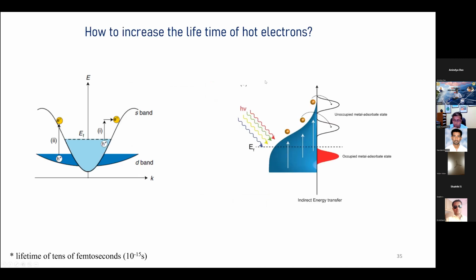So then the question we ask is, why? If the material is so black and absorbs a large number of photons, then ideally it should show good catalytic activity, better than normal gold particles, but not really significantly better. So the only way one can answer this is: although we are harvesting lots of photons and generating a large number of hot electrons, possibly the lifetime of these hot electrons is still short. They are coming back and combining with the hole, not getting injected into the CO2. That could be the reason for the low yield of the product.